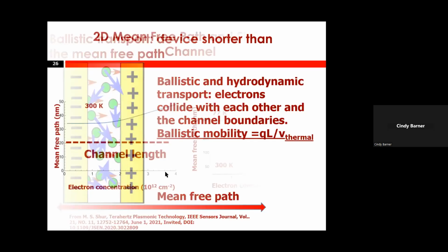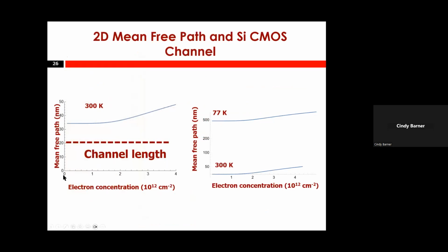Now, what happens at the contacts? Well, simplifying it very much, if the contact is metal, in a metal, scattering is very intense. Metals are very conductive because there are lots and lots of electrons, but the scattering is very, very intense. So these electrons are immediately met by other hungry electrons, impurities, interface states, whatever, and they lose their directed velocity. That's why there's this additional scattering that you could understand that way. And it is important at distances shorter than the mean free path.